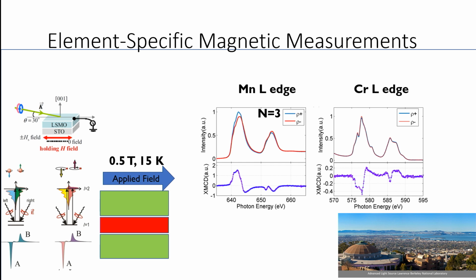In the case of chromium, we expected there to be no difference, but we found out that there was actually a difference in the intensities we measured for the two polarizations. And if you integrate that, you find out that this gives you a net negative moment. So what that tells us is that in this system here, the LSMO is ferromagnetic as we expected it to be, but the manganese here was forcing the chromium right across that interface to want to align itself in the opposite direction of the applied magnetic field. So this is something which is known as an anti-ferromagnetic exchange, where we can understand based on the orbital electron occupations why this is the case, why the manganese here is the one which is driving the chromium here to have a magnetic state, which is not what the bulk LSCO wants to be.